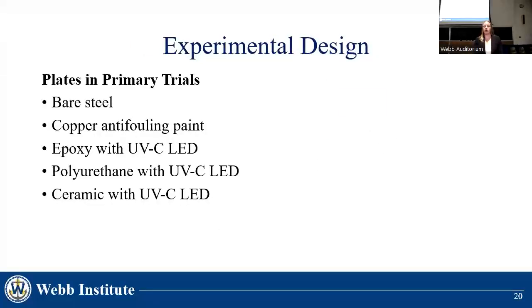For our experiment, UVC LEDs with a wavelength of 275 nanometers were selected and adhered to A36 steel plates, as this is a very common grade of steel used in shipbuilding. In previous work, silicone was used as a light distribution medium. However, to be commercially feasible, a marine-grade durable substrate must be used to distribute light that can withstand harsh conditions. Additionally, because biofouling coatings that operate on stationary vessels typically use biocides, this new task requires coatings that are not initially designed for anti-fouling purposes.